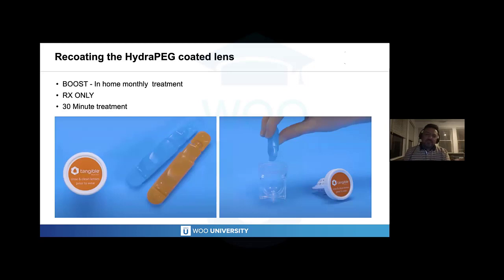So again, mentioned the Boost system. This is something that's relatively new. It's a monthly in-home treatment by prescription through providers. It's very similar, again, if you've used Progent before, where you've got a special case, you put the lenses in the case, and you're going to combine 2 vials of fluid into the case, let it sit for 30 minutes, then run it through your typical cleaning regimen. And that's, again, going to repopulate the coating on that lens where it may have eroded a little bit over the time that the lens has been initially treated or since its last Boost treatment.